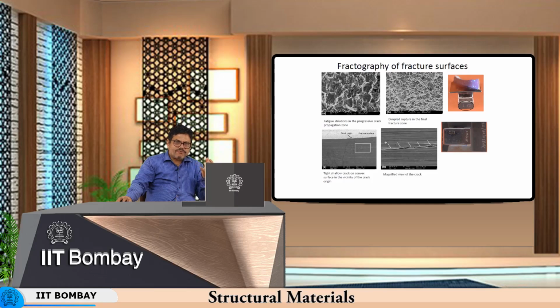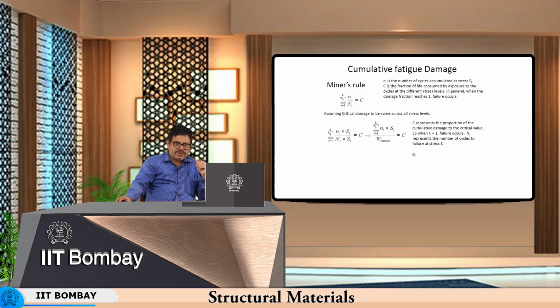As you know, during fatigue the transient softening takes place because of the reversal in the stress directions, loading-unloading type of fatigue, and therefore you have this kind of crack propagating incrementally. The crack propagates incrementally with every cycle, and then finally there is a region of fast fracture where the final fracture zone is located. So this is where you see the dimpled fracture in the final fracture zone, but the whole story started here and it propagated incrementally with each additional fatigue cycle.